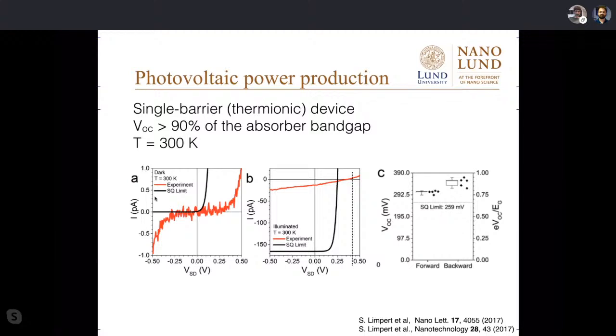So these are now IV curves. If you measure a dark current, then you see basically no current up to pretty significant voltages because you need to overcome this large energy barrier in the middle. So up to 250 millivolts, you don't see any current at all, basically. But if you turn on the light, then indeed you see a current that doesn't go through zero, meaning you have power production in this corner here.